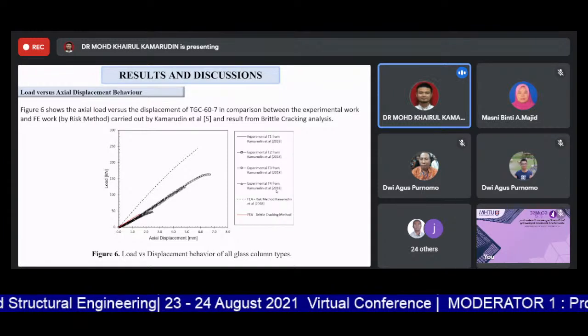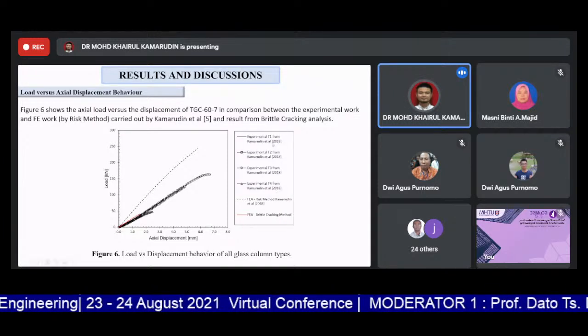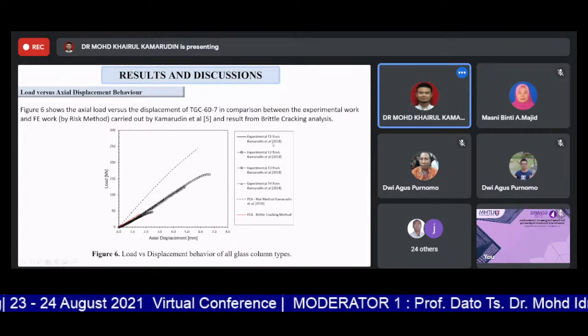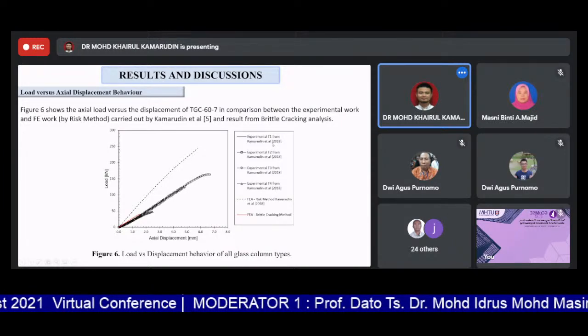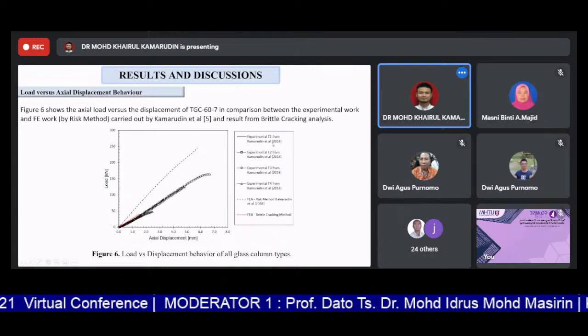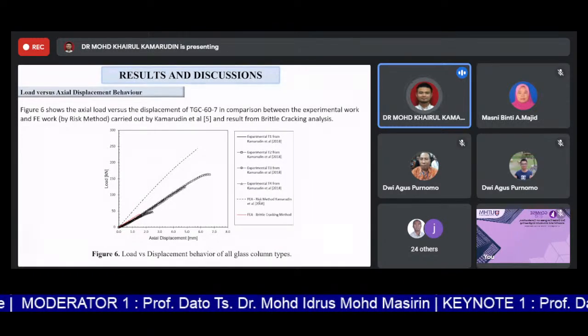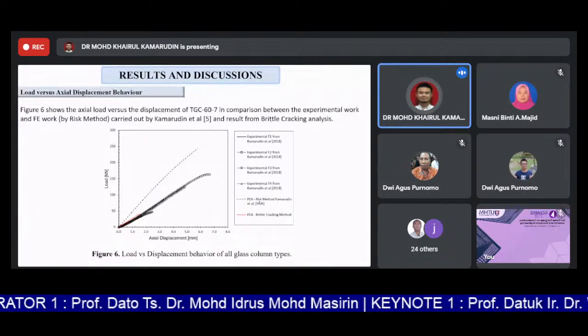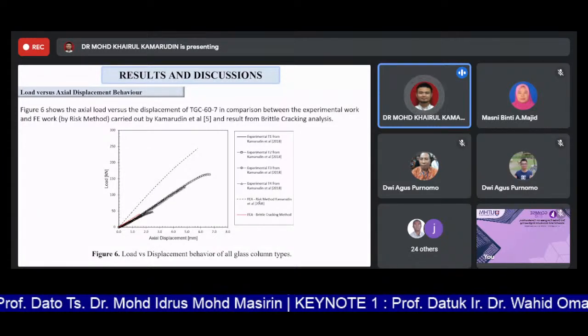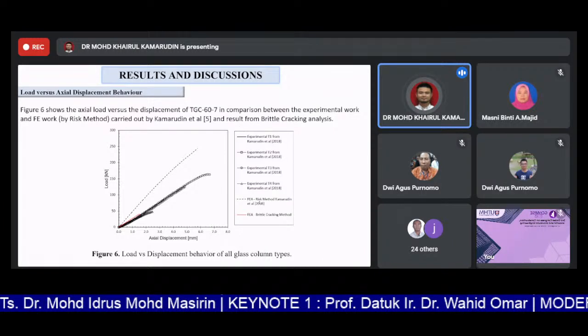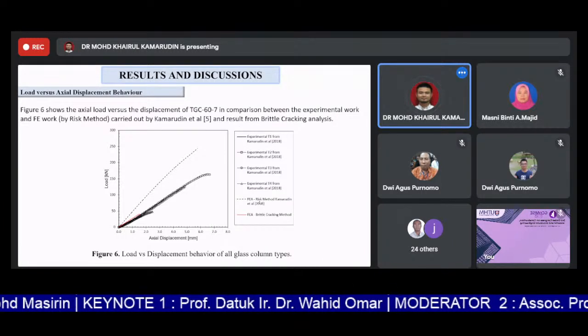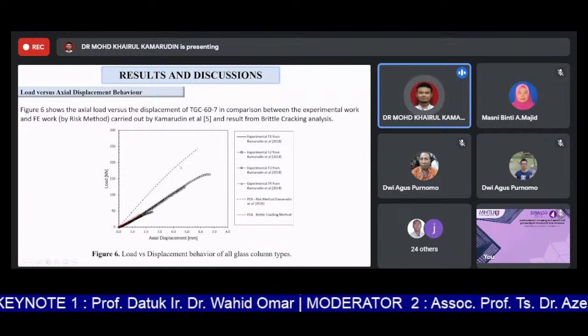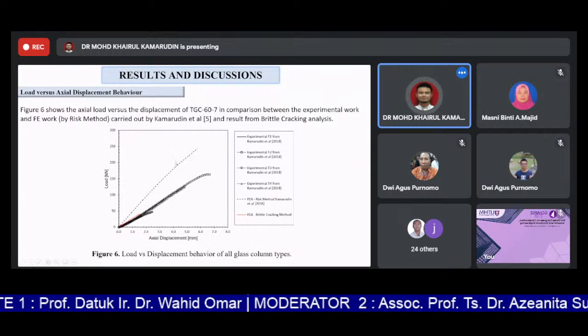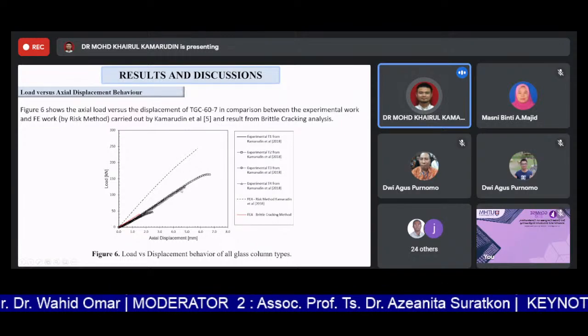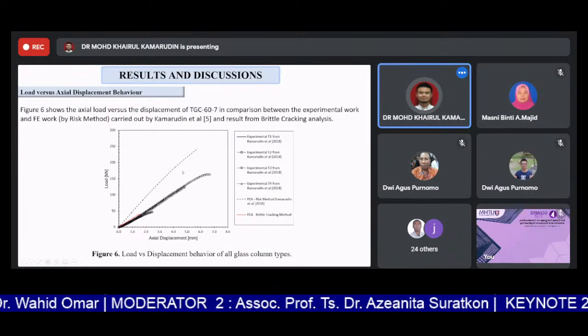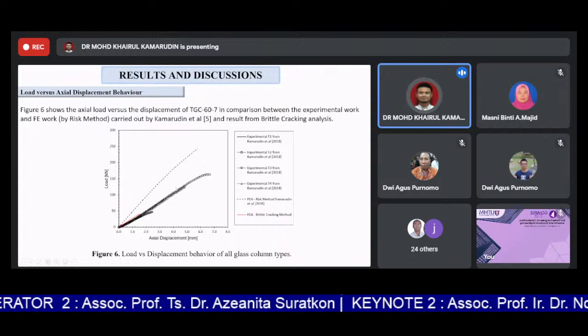So we plotted the risk method available in Abaqus, which has been used to capture the post-buckling behavior of the structure. But the result from the risk method is quite far off from what we had from the experimental work. It tends to overestimate, and the stiffness is quite far off from what we had.